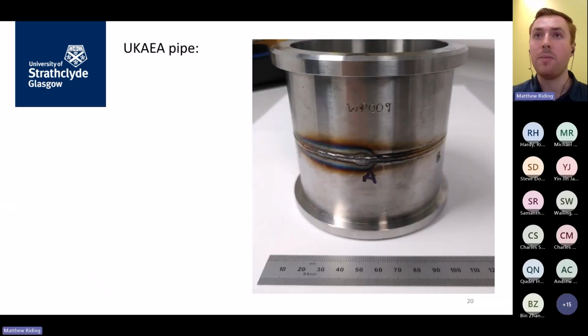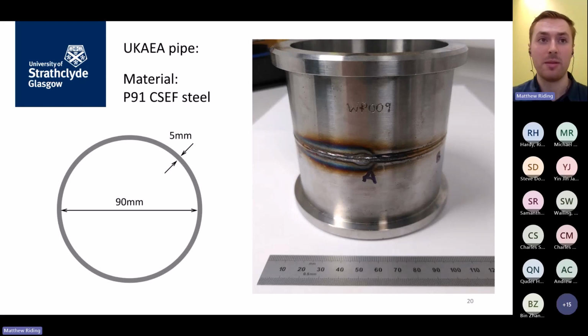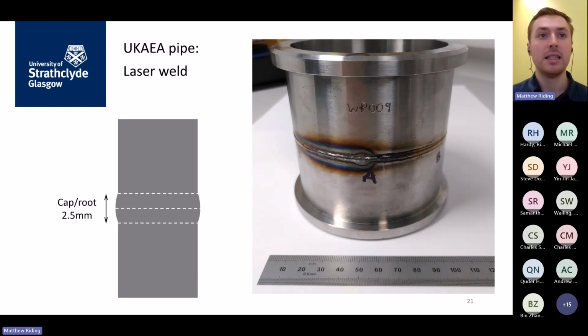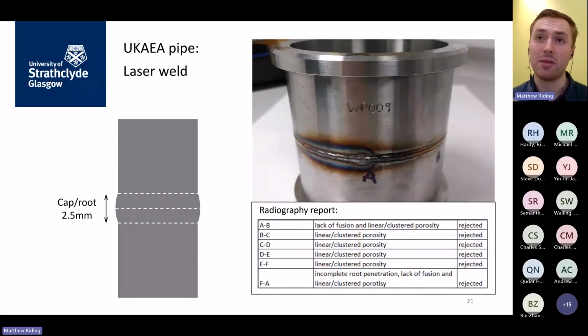Moving on to the pipe now. This is a slightly different material, a martensitic sort of nuclear grade steel, 90 millimeter bore with a 5 mil wall thickness, significantly thinner than the plate. It had a flat prep laser weld inside it, with a width of about 2.5 millimeters on both the inside and outside. It was welded from the inside using a bespoke laser welding tool at the UKAEA.